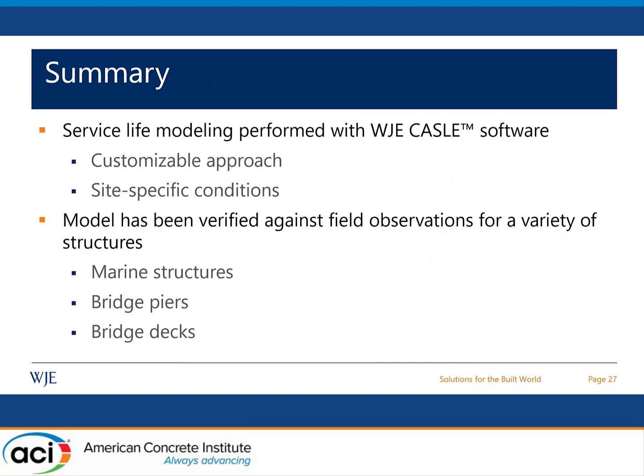So to summarize, our service life modeling was performed with WJE CASLE software, which offers us a customizable approach that we can use to consider site-specific conditions, such as the variation in chloride exposure like Marwa presented for marine structures, or the application of ECE treatment like I've just presented. Our model has been verified against field observations for a variety of structures and agrees well with the amount of damage and chloride profiles we've observed in marine structures, bridge piers, and bridge decks.